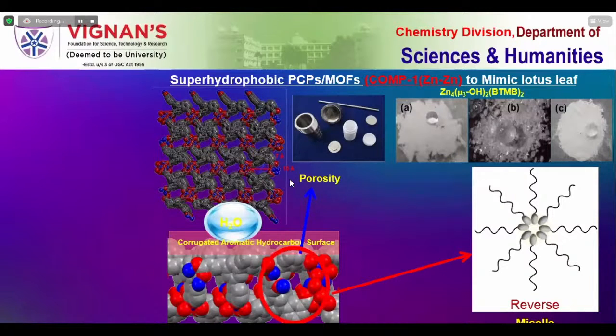See, very beautifully, when you put a water drop, similar to your lotus leaf, you can see nicely a water drop. But with most materials, when you put a water drop, even if it may not absorb, it cannot stay as a water drop, unlike hydrophobic behavior. Even in crystals, or even after removing the solvent molecules, because here my solvent molecules are there, even after removing the solvent molecules, or in powders, whatever phase we use, it is still very much super hydrophobic in nature. So it behaves almost like a lotus.